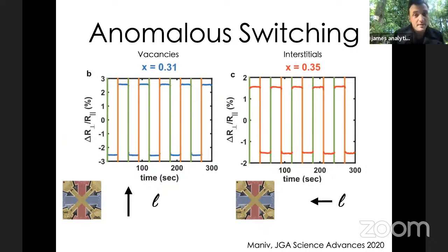Before I tell you what their results are, let me tell you about one nuance which I found very surprising. For the underintercalated samples, the ones with the vacancies, you can construct a device with this geometry where you go from a low resistance to high resistance, low resistance to high resistance, where the green and red are basically associated with whether you're pulsing east-west or whether you're pulsing north-south. If you go to the over-intercalated samples, so add some extra iron basically, and you have the same geometry, somehow the east-west pulses become high resistance and the north-south pulses become low resistance. In other words, exactly the opposite to what you see in the underintercalated.